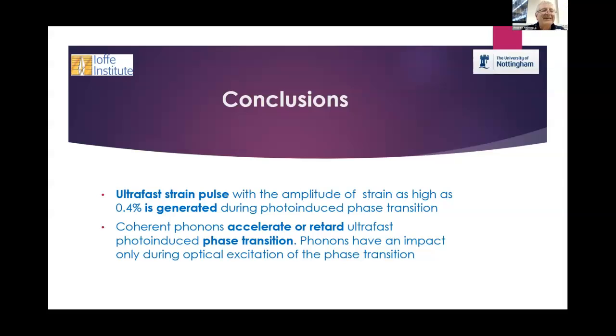Hi Andrey, very nice, I like the calibration of the strain by the nonlinear propagation. However, I'm not quite sure, it seems like you have the assumption that if you put a laser pulse, the phase transition eats up all the energy, and you are not putting more energy into the phonons if you increase the fluence. I think this cannot be quite true. So have you checked how the result changes if you continuously add energy to the phonons as you increase fluence?